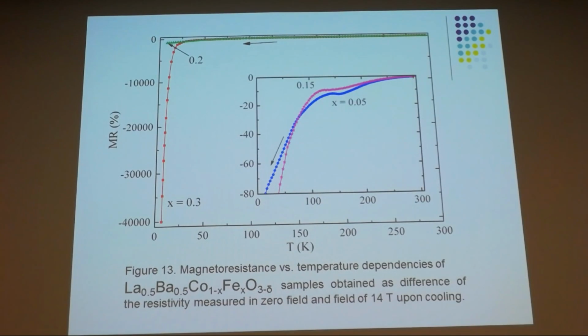First of all, we show that the antiferromagnetic phase and ferromagnetic phase in this compound are phase separated, using the neutron diffraction method. And the antiferromagnetic phase has a much larger unit cell volume than the ferromagnetic. So we propose that the antiferromagnetic phase is in a different spin state than the ferromagnetic. Ferromagnetic is the intermediate spin state, antiferromagnetic the high spin state. The high spin state has another electronic configuration than the intermediate spin state. So the jump of electroconductivity under an external field is associated with a spin transition from the high spin state to the intermediate spin state.